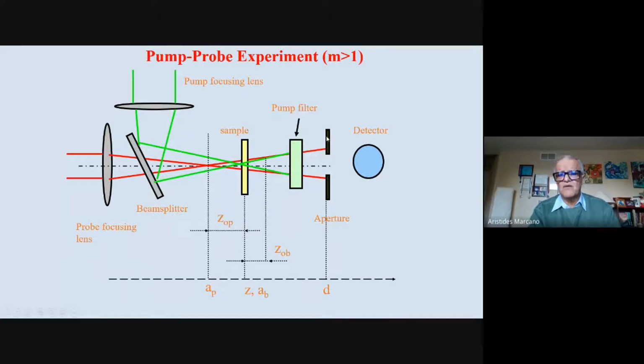And then we just put a detector. We send the transmission through some kind of aperture there, and behind the aperture we have the detector. If we have changes due to the thermal lensing effects, because you have changes in the diffraction pattern of the far field, you will see changes in the profile of the beam, and you will have changes in the energy transmitted through this aperture, and then those changes can be monitored on the detector. And that's the typical thing.